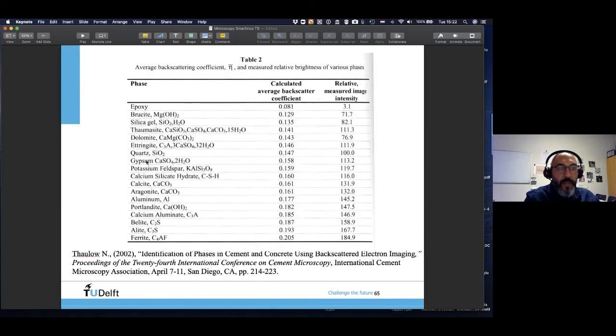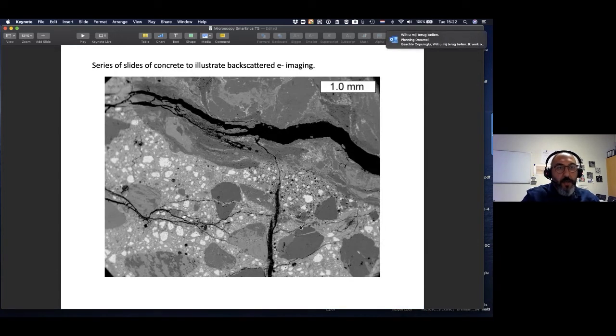You remember our table here? All the unhydrated cement grains are really high in backscattered coefficient. That's the reason you see these are all my unhydrated cement grains. And the rest, these grains are all my aggregates.